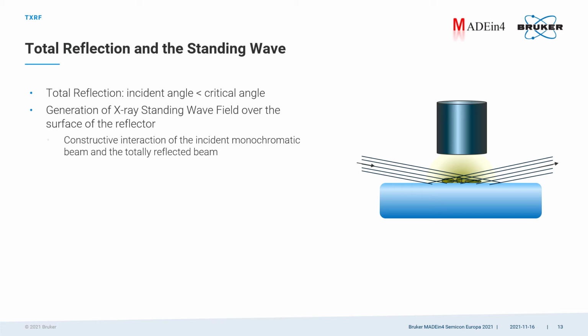In micro XRF we hit the sample at a high angle, like 90 degrees, and in TXRF we hit the sample surface at an angle that is below the critical angle of the substrate material. So therefore the X-rays do not penetrate into the substrate but are reflected on the surface. This then creates the so-called X-ray standing wave field, which is the constructive interaction between the incident monochromatic beam and a totally reflected beam. And this setup is then used to measure traces of metals on the wafer surface.